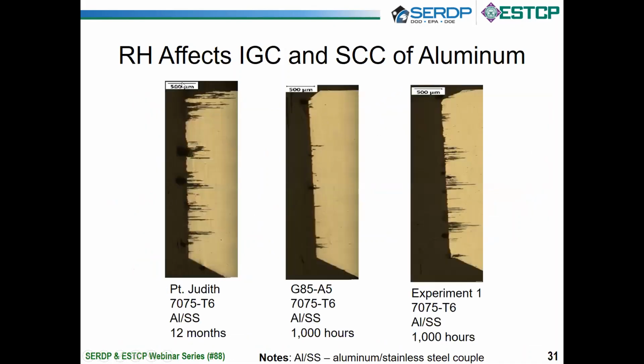Also mentioned exfoliation. So in a portion of this program, we had samples exposed outside. These are images down a fastener hole. So this is actually from Point Judith, which is an industrial coastal site that Alcoa owns. So what you're looking at is the edge of the 7000 series aluminum. What would have been here would have been a fastener, and you can clearly see the significant amount of intergranular corrosion going on in here. So this was a panel exposed by colleagues at AMCOM, that did these, and you look at that same sample, you see this intergranular corrosion in here.